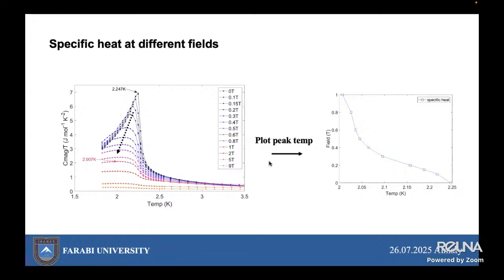In summary, the evolution of specific heat at different fields as a function of temperature. Peaks reveal a second order magnetic transition, likely antiferromagnetic, and the magnetic field suppresses this transition in a continuous monotonic manner. The constructed phase diagram provides the critical field as a function of temperature, important for understanding the stability of the ordered phase.